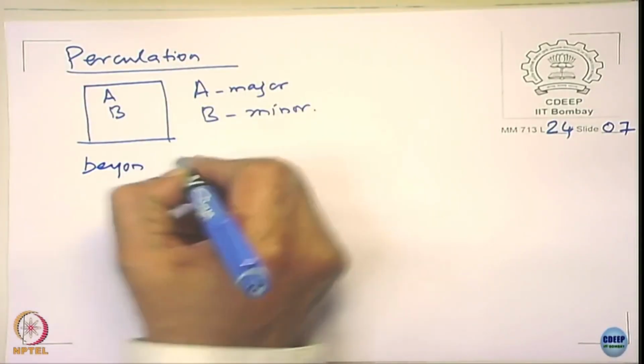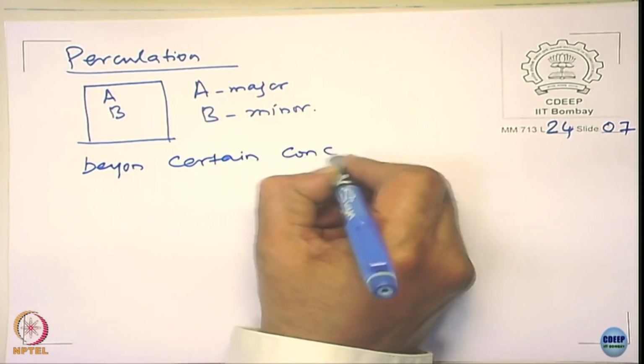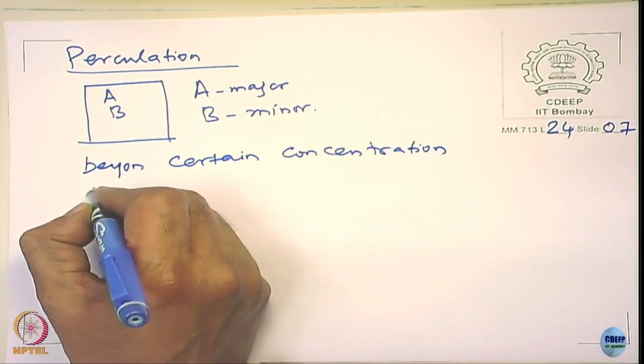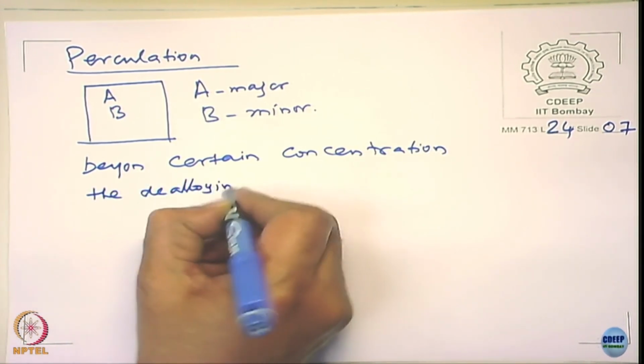Do you get it? So when I have A and B, I mix it. If the content of B is very low, then all B are isolated, okay, or all the B are surrounded by A nicely. But if you keep on increasing B at one level, B and B will come in contact with each other, okay. So that makes a continuous path for the B to dissolve, am I right? When the B and B are coming in contact with each other, then it starts dissolving actually. So the percolation model tells that beyond a certain concentration, the dealloying occurs. This is a very interesting theory.